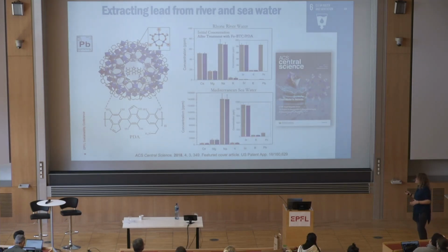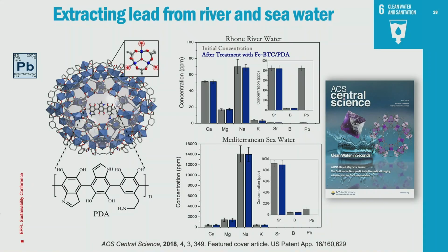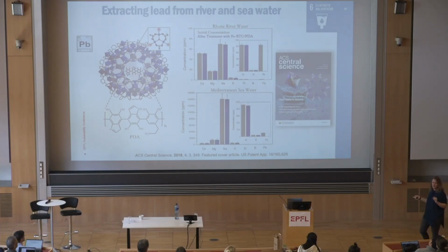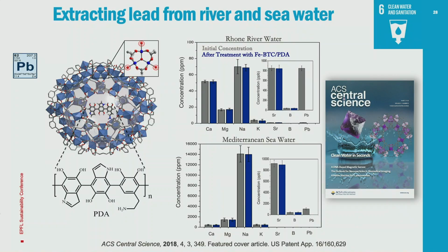And so here, then we wanted to see, well, how do they perform in really complex matrices? Okay, we'll just look at the seawater. I told you seawater is super complex. Here you can see the sodium concentration in seawater is 14,000 parts per million. We spiked it with a little bit of lead. Despite that the sodium was 14,000 times the concentration of the lead, we can still pull the lead out, and we leave behind the sodium and all of the other ions, at least within error of our experiment.